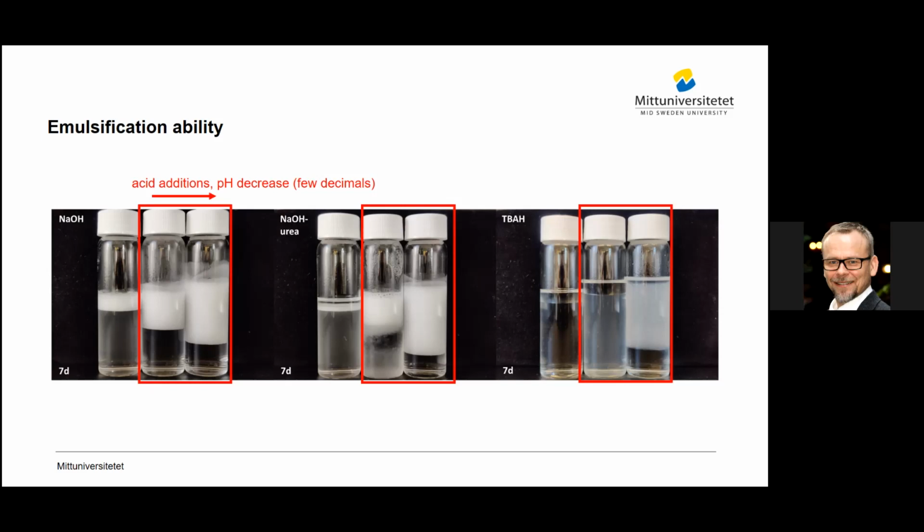You will go far away from creating a good emulsion. But the important thing here is that you cannot have too good a solvent. You need a solvent that is balancing solvency and non-solvency, you could say, to create this in the alkaline state.